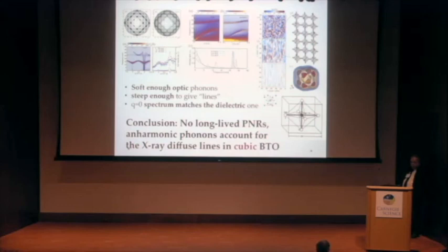So there is just one dynamics, at least at 100 Kelvin above TC, but I think it remains even down to TC. Everything can be described in terms of anharmonic phonons, one soft mode picture at any wave vector, and that's it. So I would say it's an order-disorder material with a displacive cubic phase.